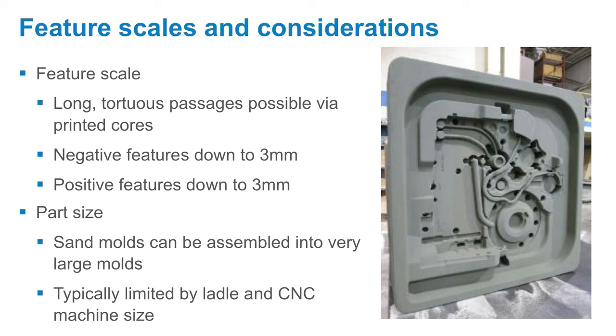So you can see some free-floating channels or core structures there that will ultimately define fluid flow channels in this casting. Typically with sand, your safe space is working with both positive and negative features of 3 millimeters. You can certainly go down finer, but that's starting to toe the edge of what's possible with this kind of synthetic sandstone.